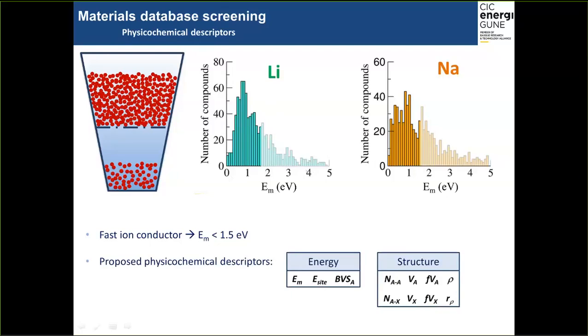So moving on to the machine learning procedure, we first propose a series of simple physicochemical descriptors divided in two main groups, energy based and structure based descriptors. In the energy based, we have the percolation energy, the cation site energy, and the cation bond valence sum. In the structural ones, we find things like the cation-cation and cation-anion coordination numbers, the polyhedron volume of the cation and the anion, the cation-anion volume fraction, the density of the material, and the percolation radius, this RP.